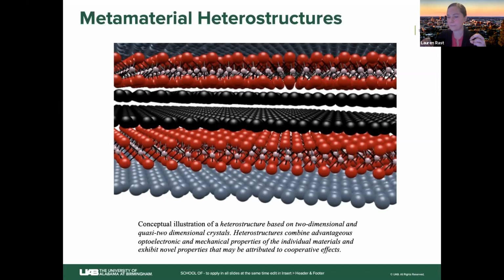So again, these metamaterial structures, these heterostructures, which have layers of different 2D materials within them, combine the advantageous optoelectronic and mechanical properties of these materials, and they also have cooperative effects that are emergent phenomena just of the heterostructure, that you wouldn't see for the individual material properties.